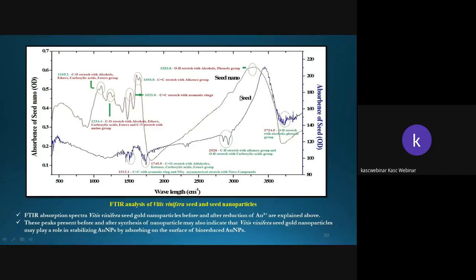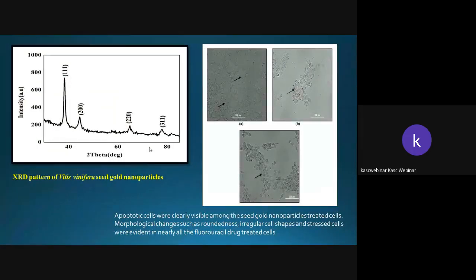At 3724.5, the grape seed showed the presence of a strong peak. This is the O-H stretch of the phenols and alcohols with hydrogen bonding. The sharp peak at 2926 represents the C-H stretch with the alkane group, and the O-H stretch with the carboxylic acid group. And the band at 1755 is a carbon-oxygen double bond stretch with aldehydes, ketones, carboxylic acids, and ester groups. So these all show that the gold nanoparticles are also combined with the phytochemicals which are present in the seeds.